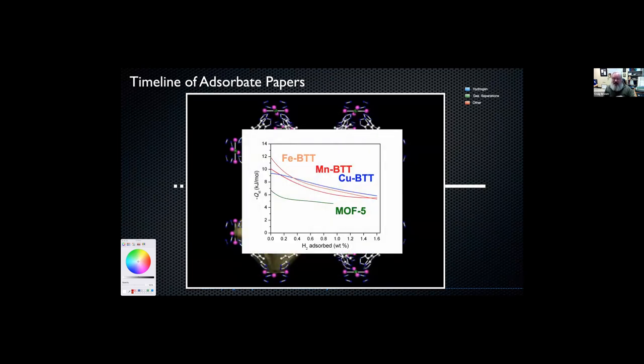The interesting thing about the entire series here is that despite some of them being more solvated than others, like the manganese is more solvated than the copper and the iron is not solvated at all, there's an increase in enthalpy for adsorption for the hydrogen compared to a metal organic framework that doesn't have exposed metal sites. And the increase in enthalpy for adsorption was seen as a mechanism to improve the performance characteristics of a prospective hydrogen storage medium towards room temperature.